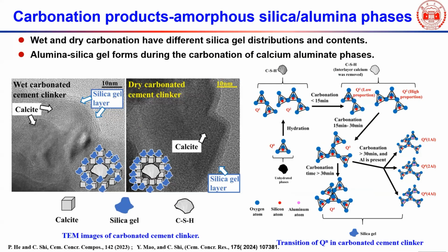The other interesting thing in carbon mineralized products is silica gel. Solidia actually copied my idea and tried to market the technology. But on the other hand, there are very serious issues with their process. Now they changed the marketing strategy. Now they try to produce Solidia cement, then carbonate it and sell it as supplemental cementitious material. So I kind of understand: they use such a high temperature, such a complicated process, and then produce a supplemental cementitious material, not cement. The reason is that for Solidia cement, they use very low calcium.